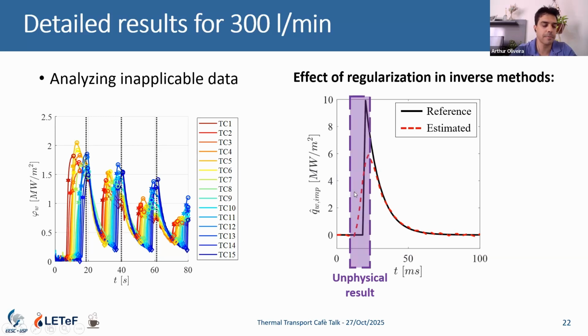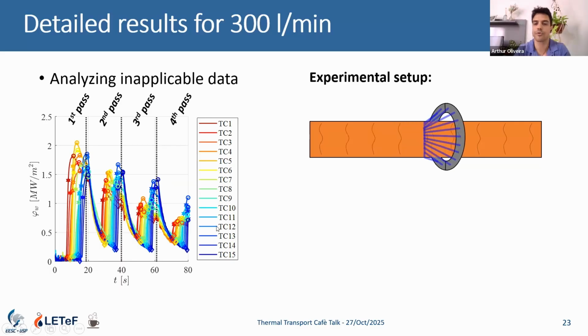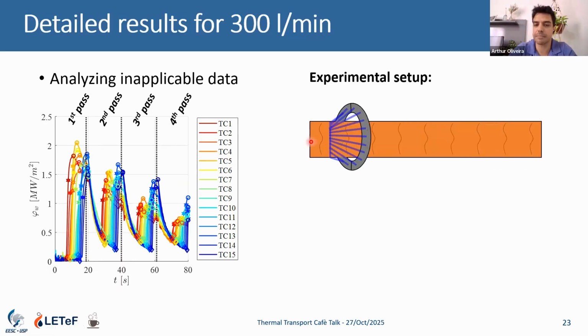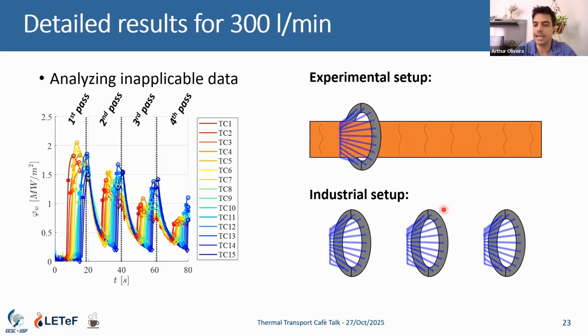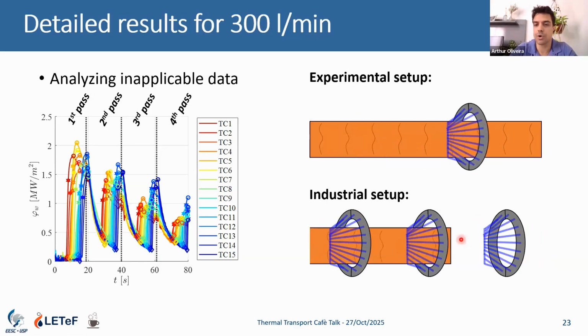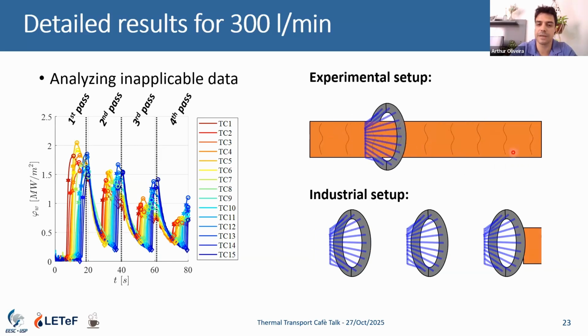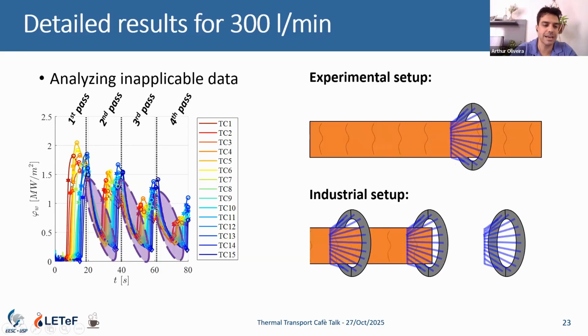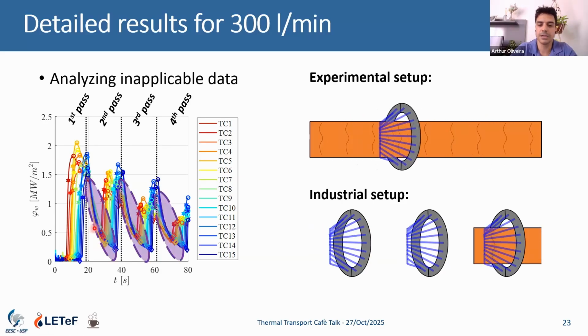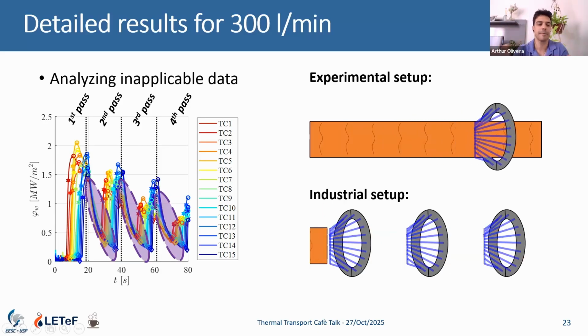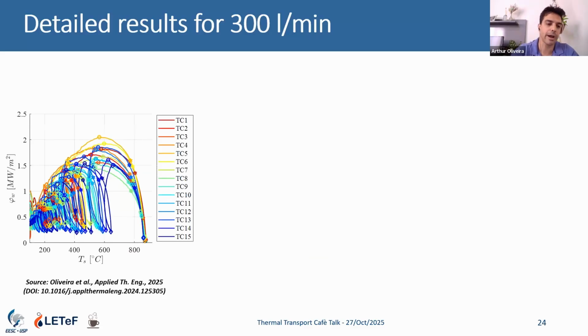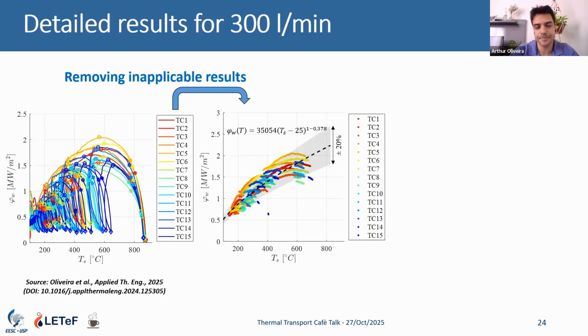So considering our simulations, our results with the bar cooling, this rise in the heat flux must be neglected. Also, considering the industrial process, our test has the static bar and the ring sweeping the bar, but in a real industrial process we have several rings and the bar is passing inside the rings. So we don't have this dry moment of the bar in our industrial setup. So we can try to neglect also this heat flux decay, to try to represent the industrial case in our experimental setup.